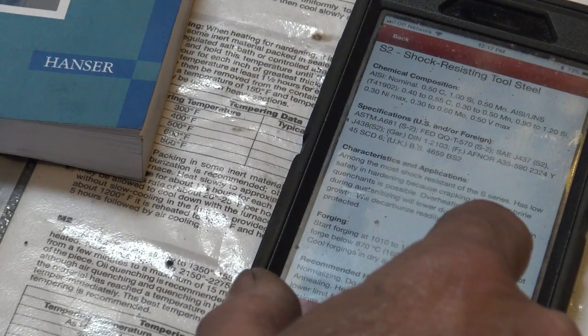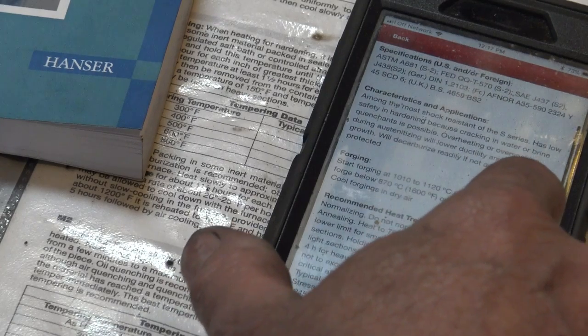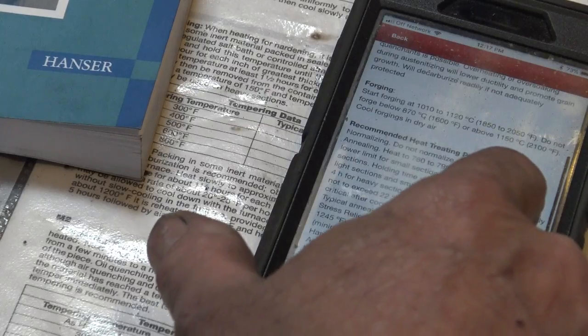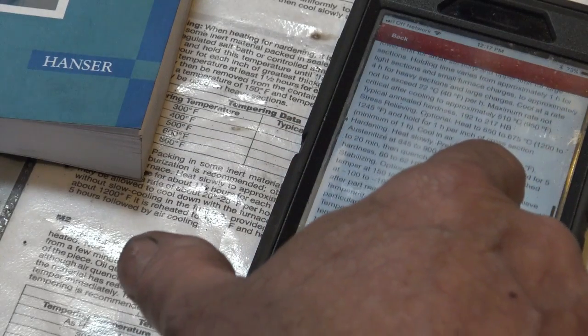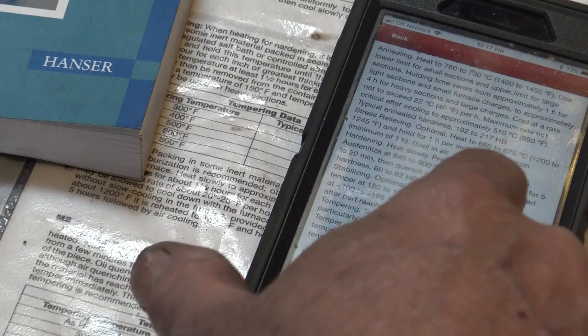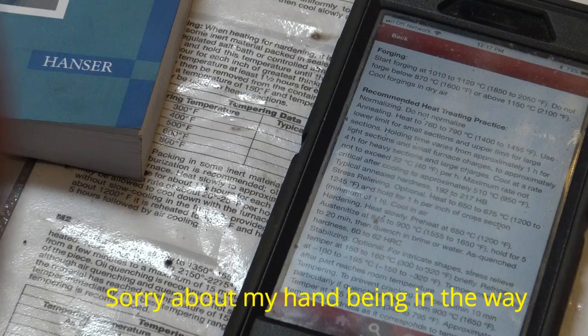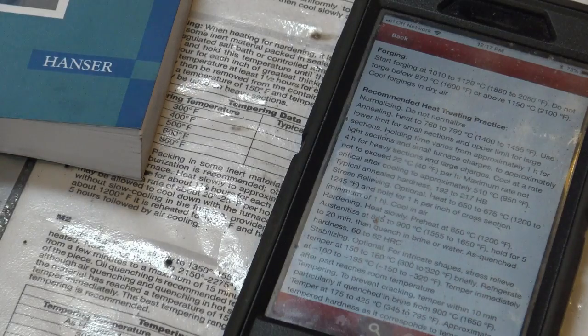It'll tell me the chemical compositions, the specs, the characteristics, the applications, forging guidelines, and recommended heat treating practices, including all the temperatures for annealing, hardening, tempering. When we talked about annealing, it says heat to 1455, use lower limit for small sections, and so on. Hold for 1 hour, then cool at a rate not to exceed 40 degrees per hour until it gets down to 950 degrees. So that's what it thinks you need to do to anneal. It doesn't say anything about vermiculite.